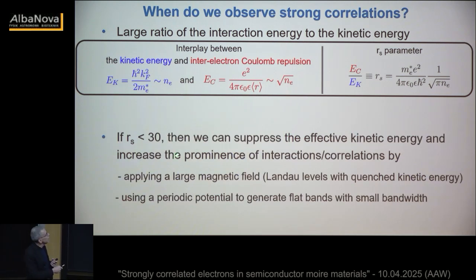There are actually two possibilities, if rs parameter is small, that physicists have explored over the last 40, 50 years. The first one is to apply a large magnetic field. If you apply a magnetic field, you know that electrons make cyclotron orbits. So in quantum mechanics, they form Landau levels, and these Landau levels have no energy dispersion. So you have a high density of states with identical energy. And that actually satisfies this condition that effective rs could become large, even though one should not use this formulation in this case, because there is no kinetic energy cost. The only energy scale is that of interactions. Okay, so in that sense, the system is bound to exhibit interesting correlated states. And this indeed is the reason why fractional quantum Hall states appear and have been studied as the prototypical strongly correlated system exhibiting fractionally charged excitations.